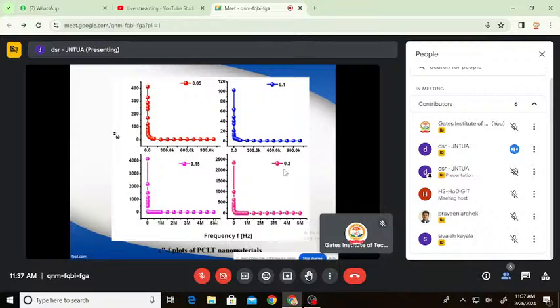The grain boundaries seem to be more active at lower frequencies, while grains exhibit more activeness at larger frequencies. This has been reported in the literature. It is also known that grain boundaries describe large resistivity while the grains reveal low resistivity. Hence, all the samples revealed high values of epsilon dash and epsilon double dash at lower frequencies. Further, the space charge is found to be dominant at low frequency, which leads to large polarization and hence larger epsilon dash and epsilon double dash.